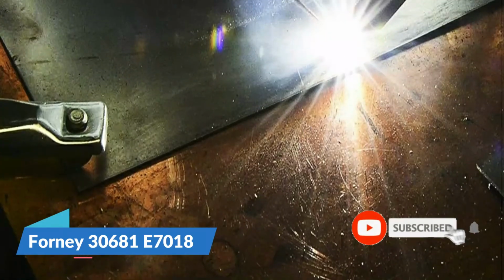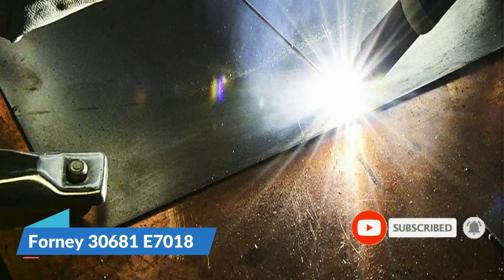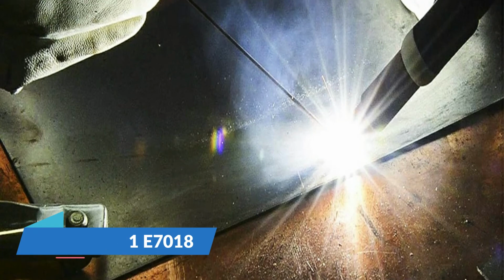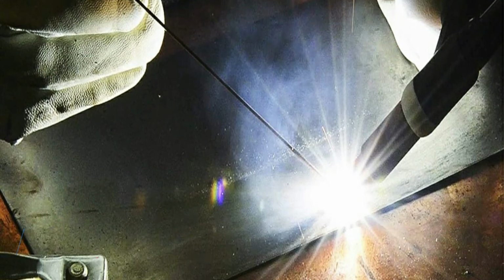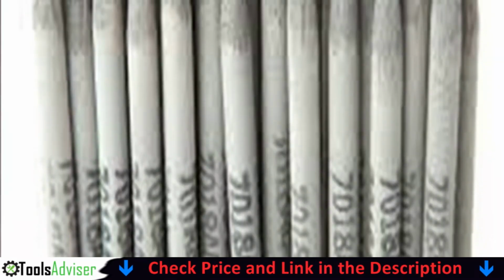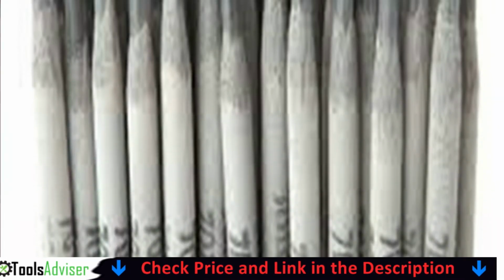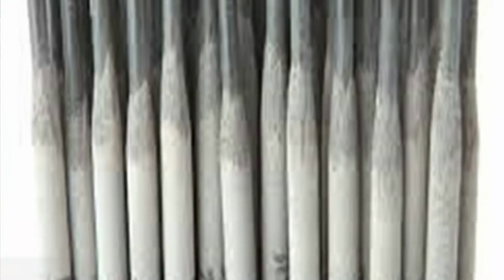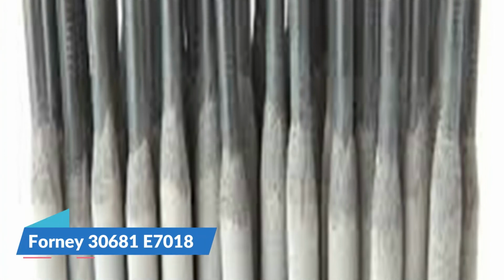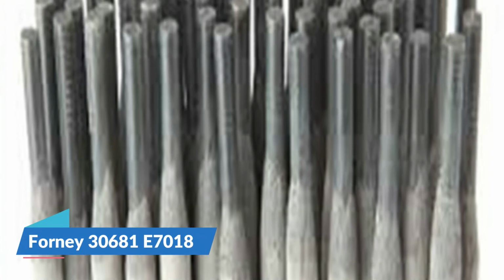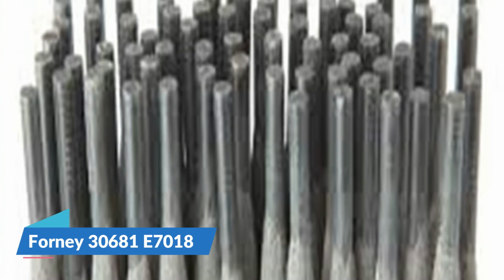Number 1 is that they flow and penetrate beautifully even at 90 amps on the little welder, and number 2 is that restriking is very easy, which is almost unheard of on 7018s. I'd recommend this rod without the slightest hesitation. Excellent bead contour, light spatter and slag is often self-cleaning. Excellent for tack and skip welds, offers easy restriking, ideal for out-of-position welding.